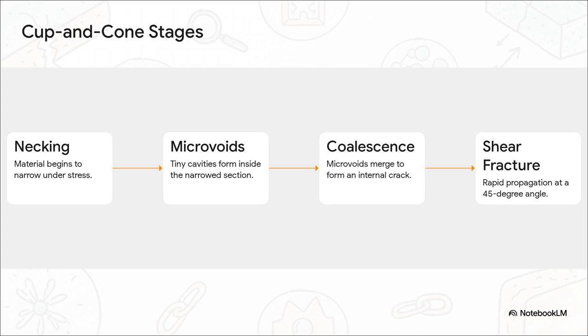The cup and cone fracture actually happens in 4 very specific physical stages. First up is necking, where the material just starts to narrow right in the middle as it's being pulled. Second, tiny microscopic cavities, called microvoids, form inside that narrowed section. Third, as you keep pulling, those microvoids coalesce. They literally merge together to form an internal crack. And finally, that crack shoots around the outer perimeter, shearing off at exactly a 45-degree angle.